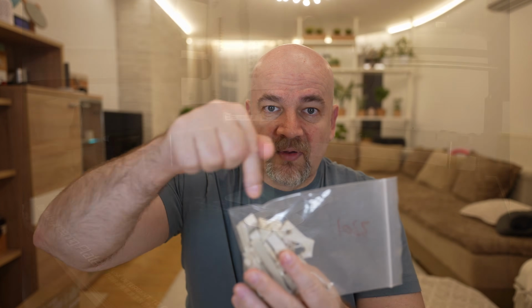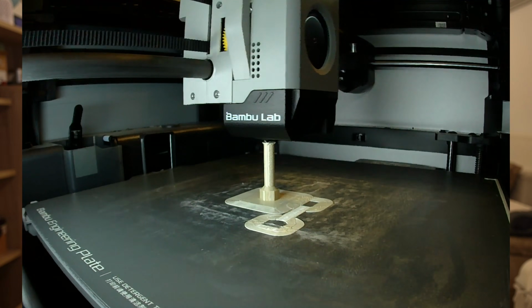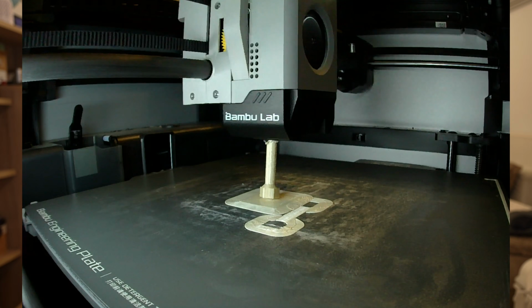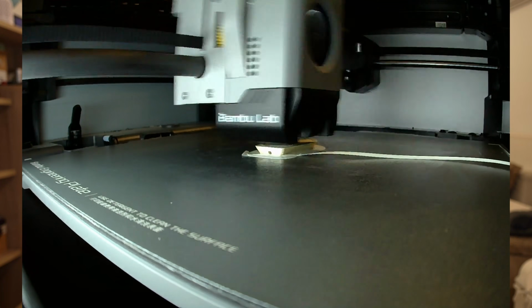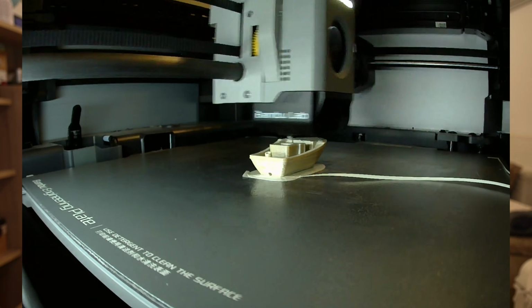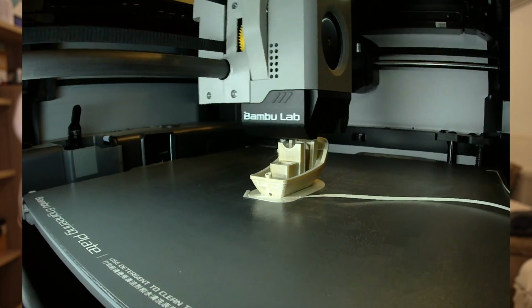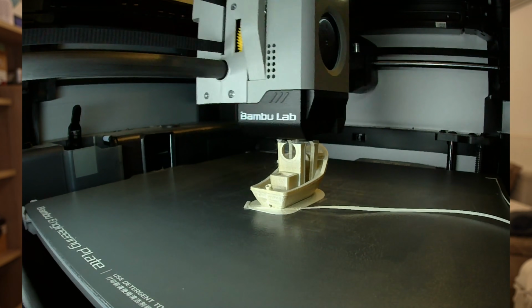Now there is a problem with the printing too. We need good layer adhesion, especially with the materials which tend to warp. Because in this case, during the printing, the nozzle will create some side force because of that friction, and then we need good bed adhesion and layer adhesion to resist this side force. And you saw a typical example, that Benchy. It was almost finished, but at the end the material curled up a little bit and just a small side force broke it, and actually it was a failed print. So I believe that some improvements are required here.